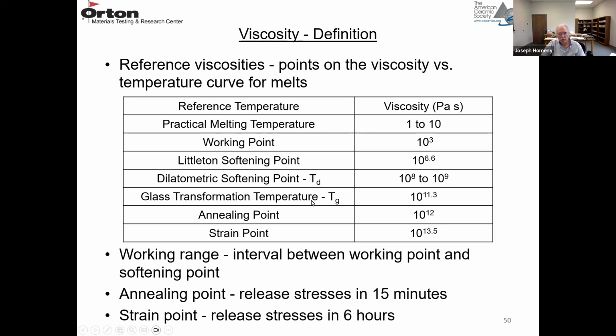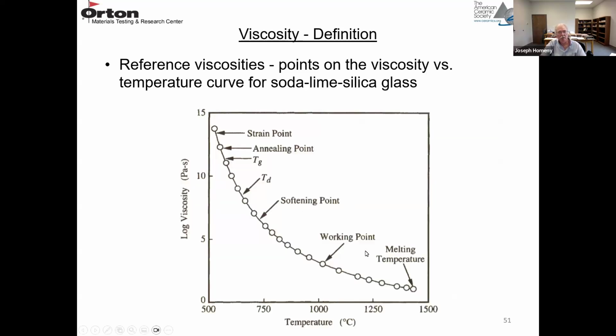The glass transformation temperature is 10 to the 11.3. And then the annealing point is 10 to the 12, and the strain point is 10 to the 13.5. So the working range where you can actually form a glass is between the working point and the softening point. The annealing point, which is 10 to the 12, is a pretty rigid material, but you can relieve the stress that forms when you cool it in 15 minutes. And the strain point, 10 to the 13.5, is still quite rigid, but you can relieve the stress in about 6 hours. So those are the different reference temperatures.